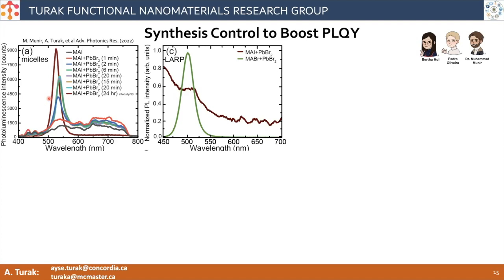So I'm showing an example of what's called ligand-assisted reprecipitation, which is a very common approach to making nanoparticles. But if you're mixing together, for example, methyl ammonium iodide and lead bromide, you don't really get a good solid emission. But if you use a micelle technique, you can get a high yield of around 40 or 50% conversion of light into emission.